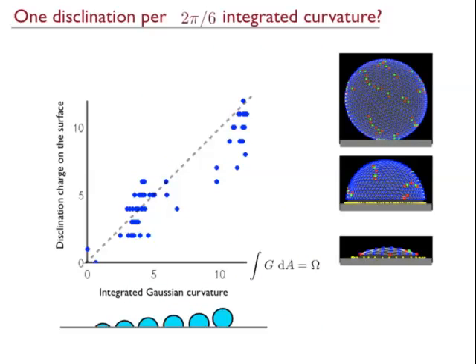So the first question is, we want to know when we make domes. So we know that you have 12 5s, 12 pentagons on a sphere. Now I want to make a dome. I want to go from a disk that's flat, where I know there are 6 on the boundary, and I want to start inflating it until all I'm left with is a little patch at the bottom, and I essentially have a complete sphere. I want to know how many are on the edge and how many are on the surface. So I'm going to look at how many disclinations there are, the total disclination charge on the surface in terms of the integrated Gaussian curvature.